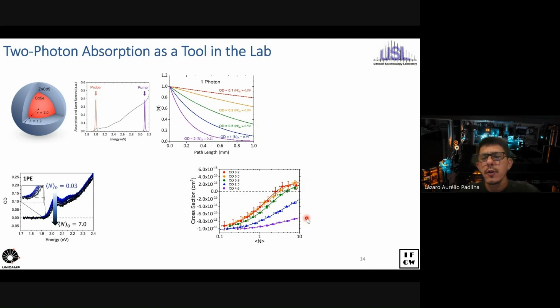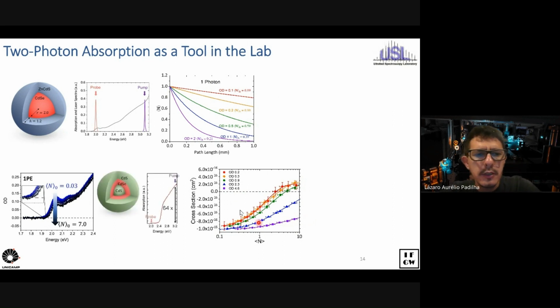So two-photon absorption comes as a tool to solve this problem, especially if you're looking into these very interesting nanomaterials with thick shells, where the pump excitation wavelength has much larger optical density, or much larger absorption cross-section, than the probe region. That would make it nearly impossible, because see, this is the optical density for the pump.